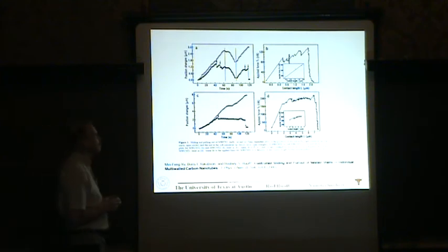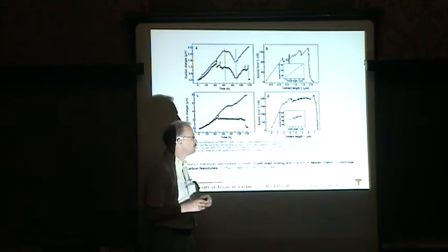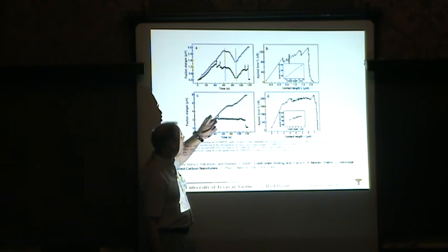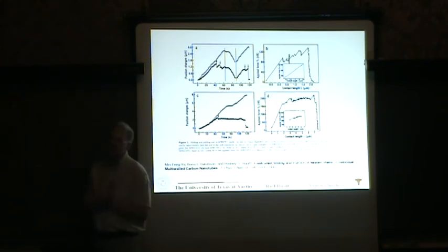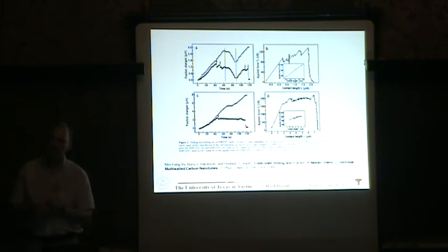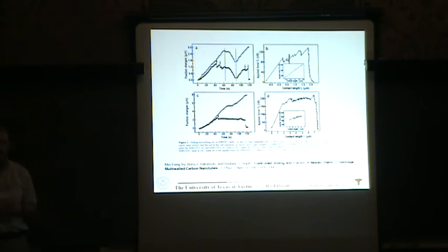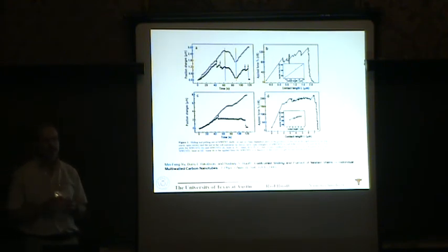But the other multiwall carbon nanotube had almost smooth pull-out once we overcame the stick and the slip started. And it had a fit value for the shear strength of about 0.08 megapascal. And this caused us to conjecture about the possibility of frictionless sliding. It's now going to be visited by other people as well.